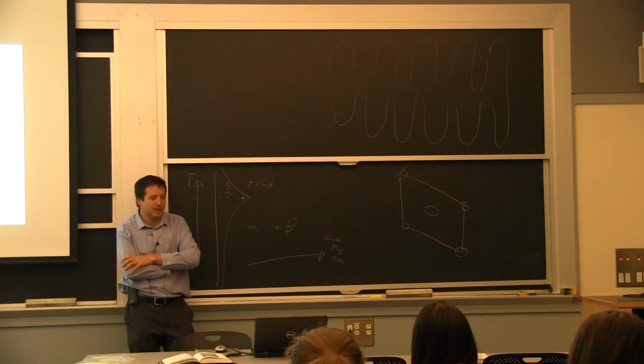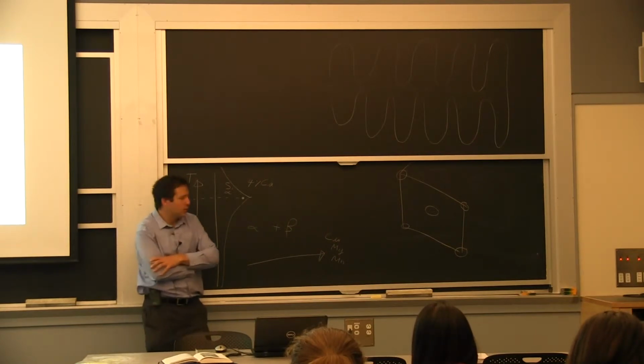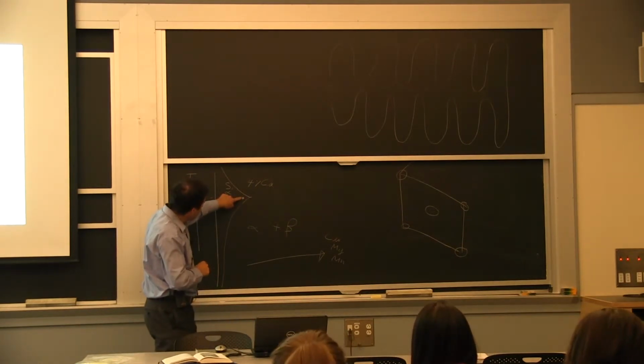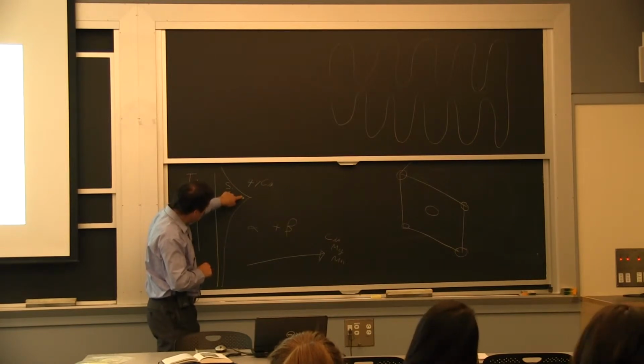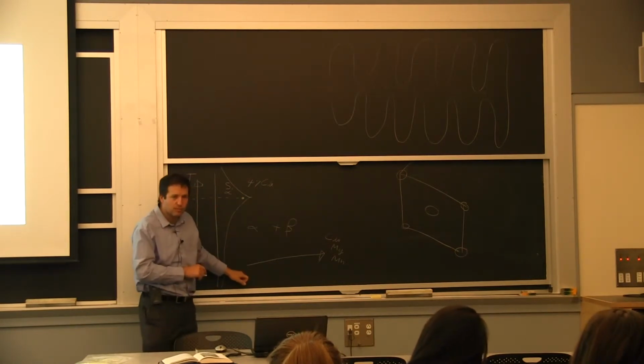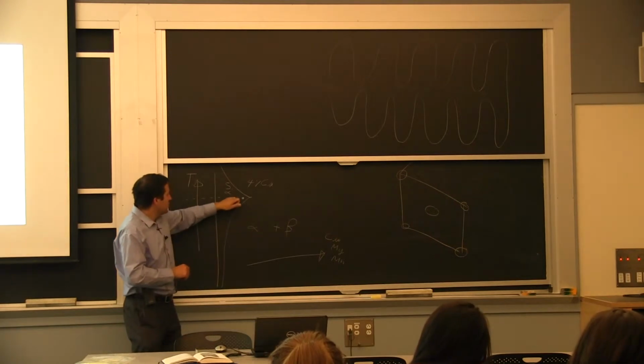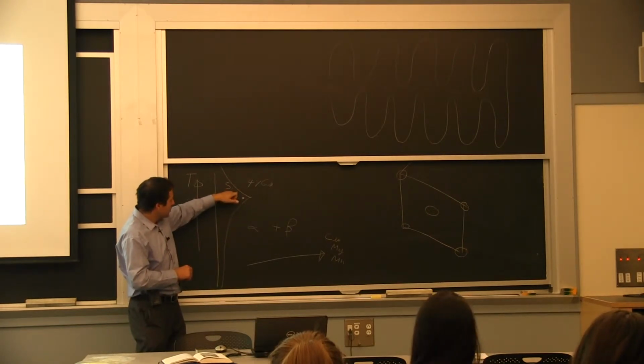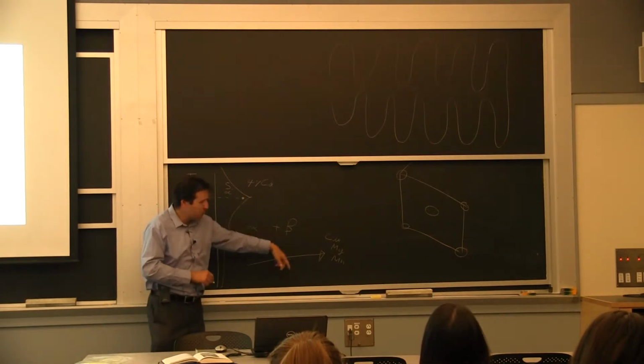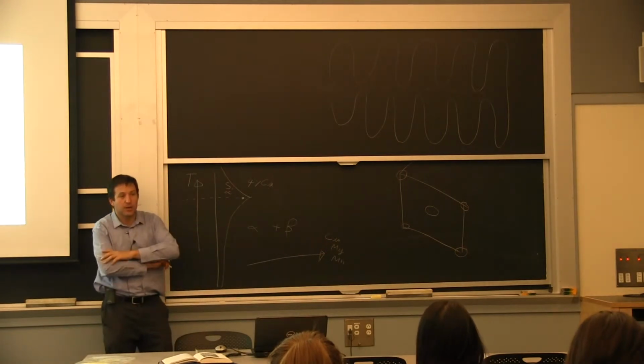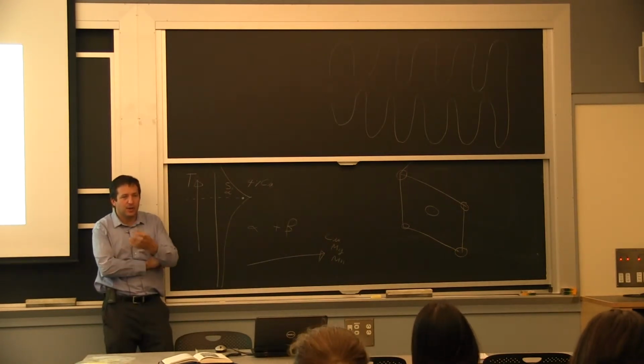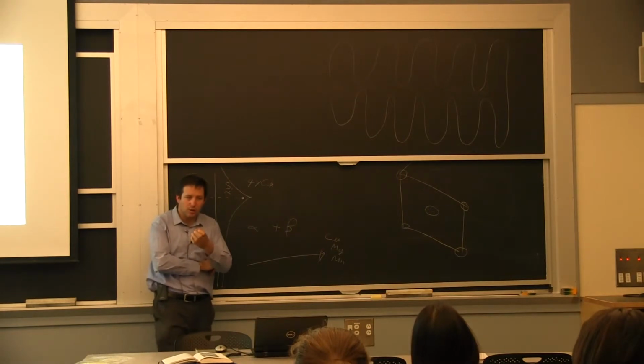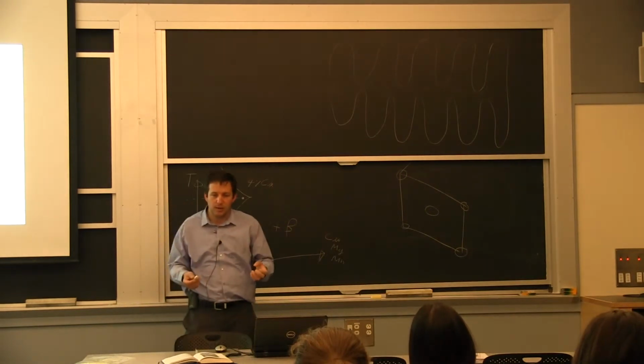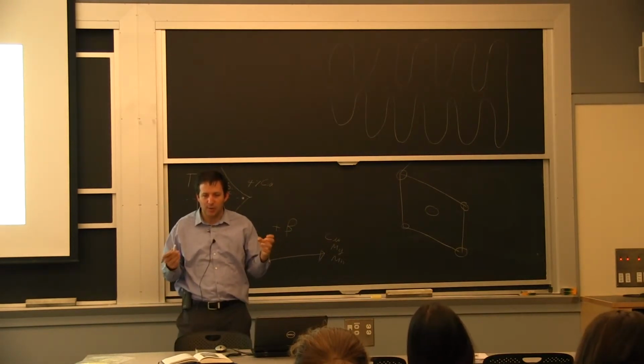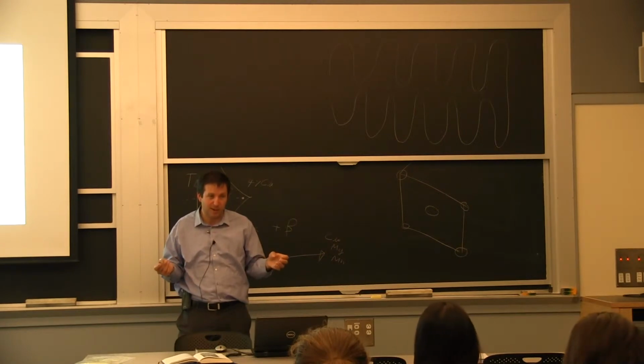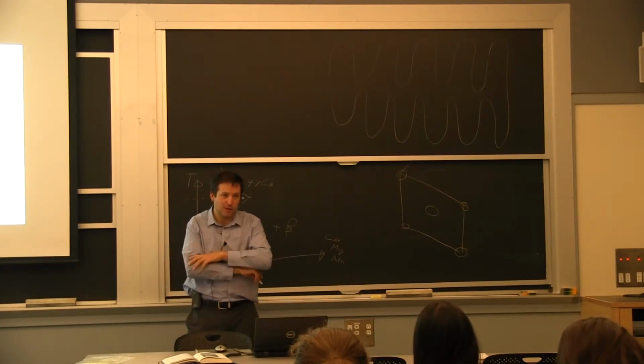If, on the other hand, you quench completely from this point of homogeneous composition down to ambient temperature, you essentially supersaturate your structure with the copper, the magnesium, and the different alloying elements. Now you have a potential, because you're at such a low temperature, where there are some alloys that would actually form precipitates over time at ambient temperature, the 2000 series aluminum.